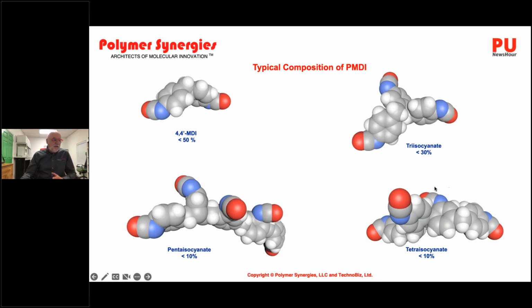is less than 30%, tetra is less than 10%, penta is less than 10%, and there are still higher oligomeric species. Now, the reason I show you this slide is I told you earlier that when you're formulating your adhesive or your coating or whatever polyurethane, you should think about your chemistry from a structure property perspective. So if you're formulating with pure MDI or 4,4 MDI, this is a symmetric molecule, and it's the smallest molecule in the PMDI mixture.